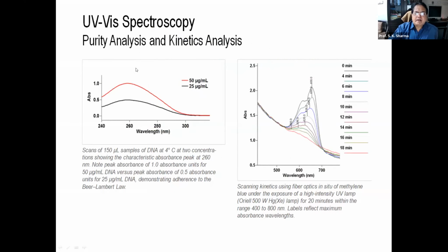Okay. And purity analysis and kinetics analysis. Kinetics means how these concentrations change with time. You can see the characteristics of these chemicals, or some reaction that is taking place in the cuvette with time. At 0 minute some peak is there. As time passes, different peaks appear. At the bottom you can see 18 minutes; the red one is the 18 minutes. So after 18 minutes, your curve becomes like this. It means whatever chemicals were present here showing a high peak tend to disappear with time. They reduce and disappear, and your curve becomes smooth like this.